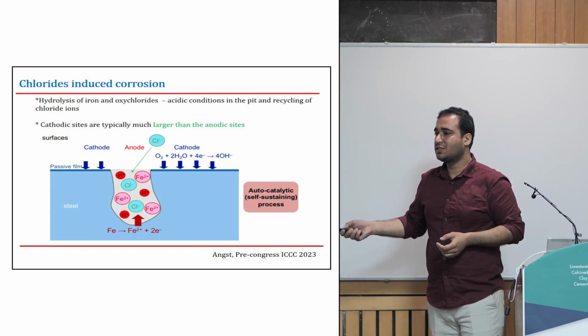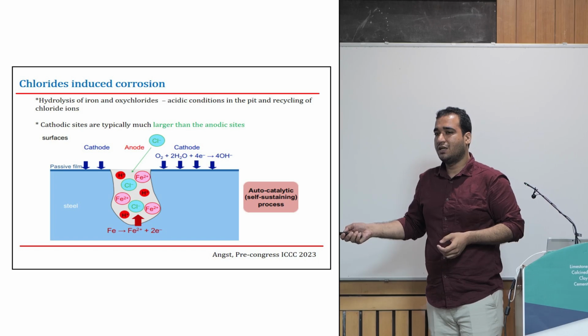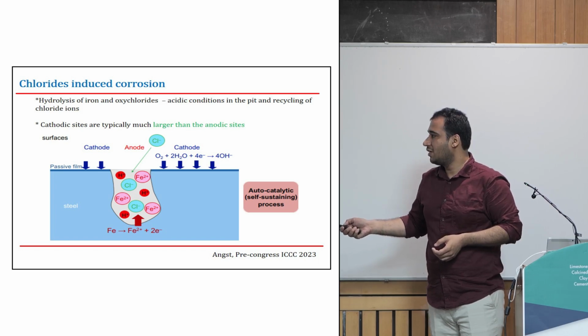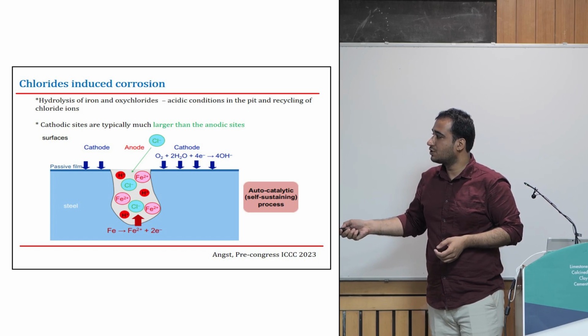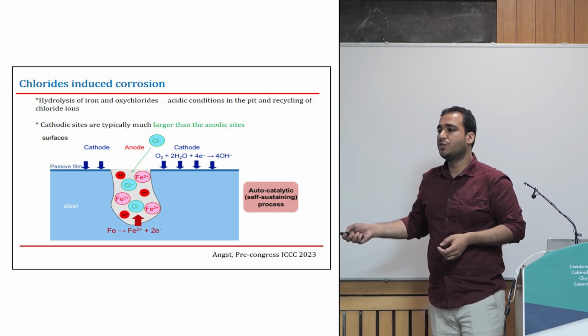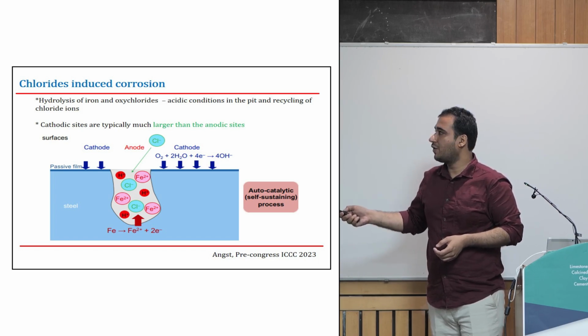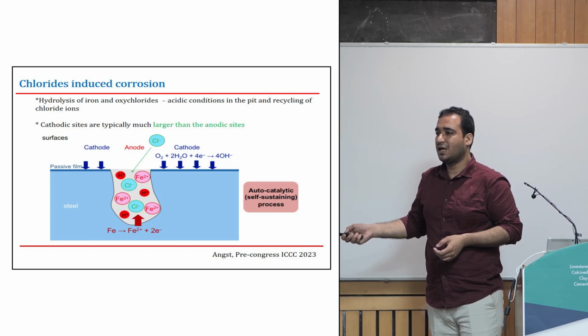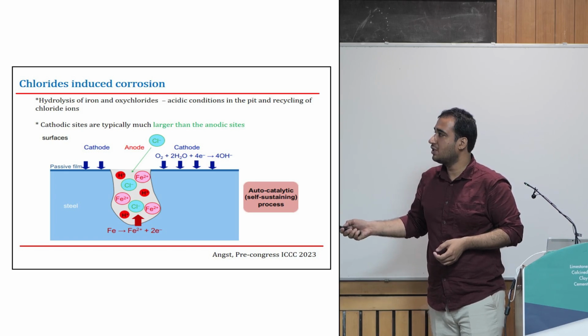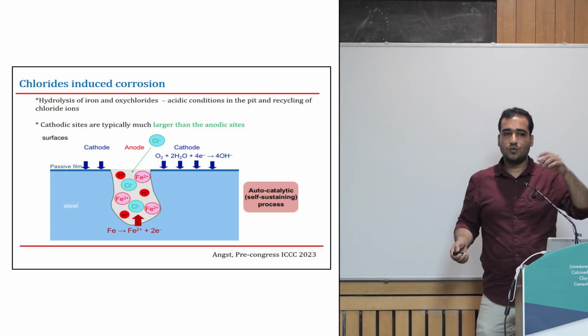And if we know the influence of pH on the corrosion rate, we know that under acidic conditions it's much more aggressive than under near neutral or alkaline conditions, and we get an autocatalytic process because these chlorides don't get consumed in this process. Because of hydrolysis they keep on getting released and still maintain the concentration here, and we get a very aggressive situation which leads to a much more drastic loss at the same point.